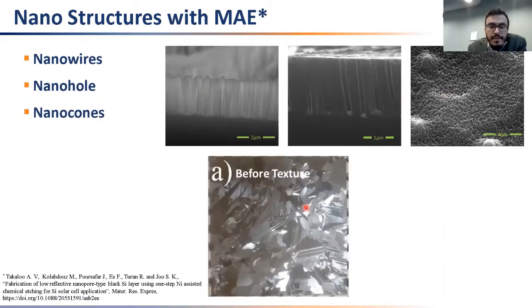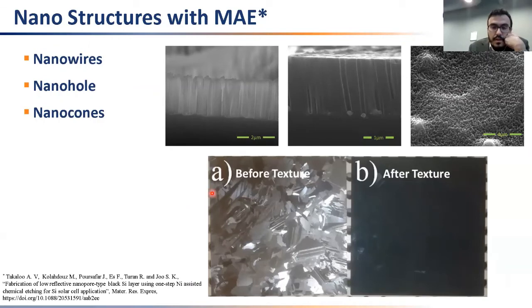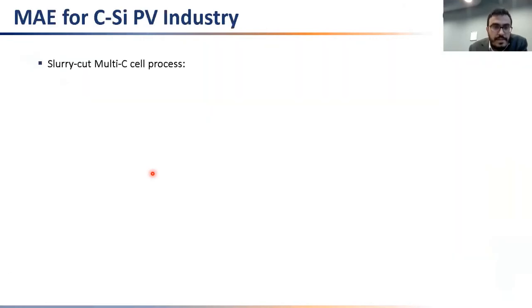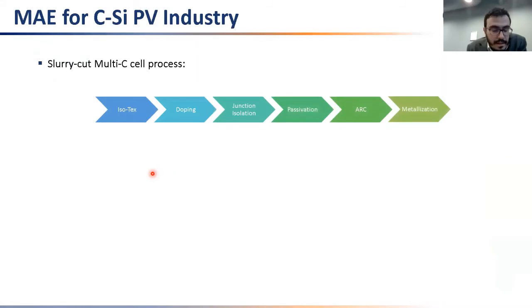And before texturing, your multicrystalline wafer looks like this. It's pretty shiny, but when you make this nanotexturing, you get a completely black solar cell, which means that you are having very low reflection from the surface, so you can harvest the solar energy to the limits. And this is called the black silicon concept. And this concept is applicable to industrial silicon solar cell production.